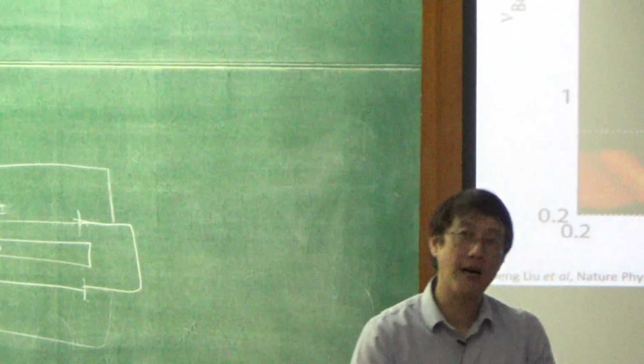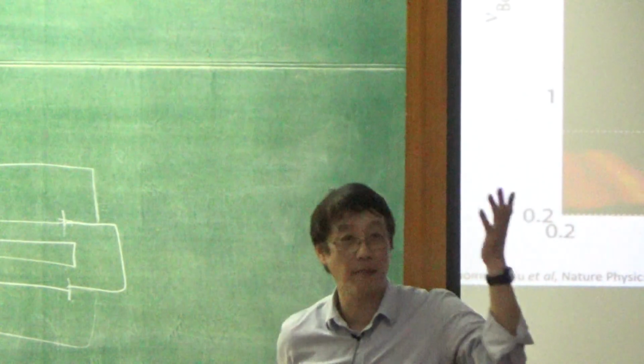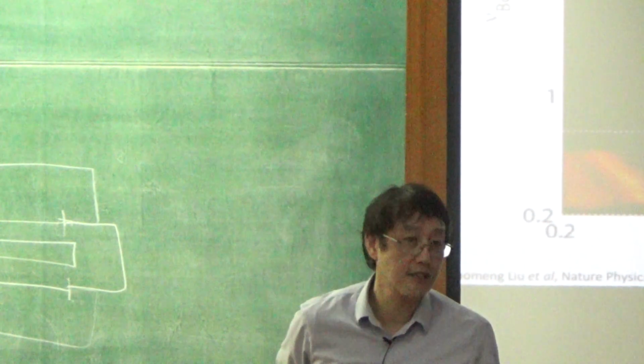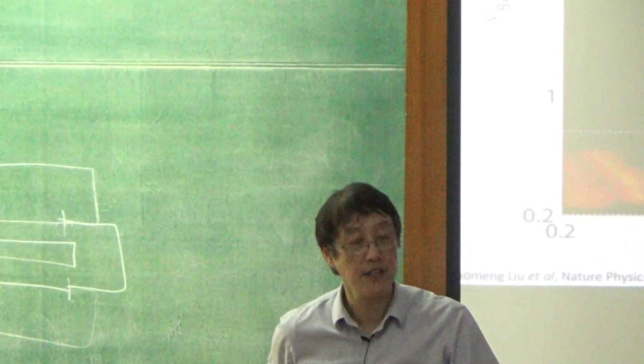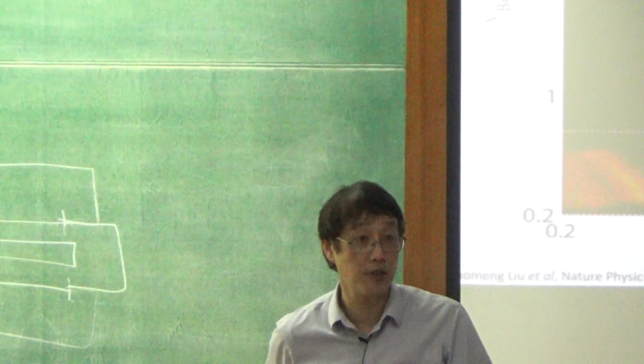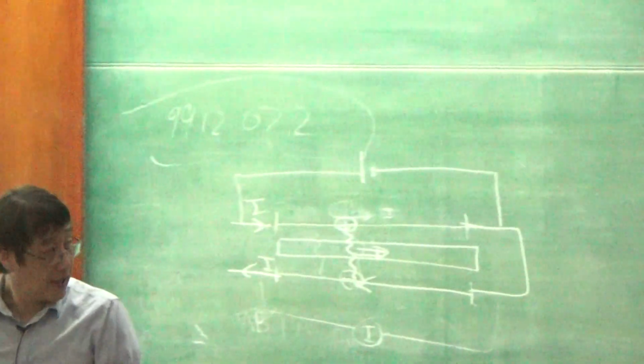It turns out about 1 nanometer and above of boron nitride, say 3 layers and above, you strongly suppress the tunneling between them. So it's okay. But below that 3-layer limit, you start to suffer from the tunneling between them, which actually spoils all this physics, right? So there is some sweet spot you have to choose.